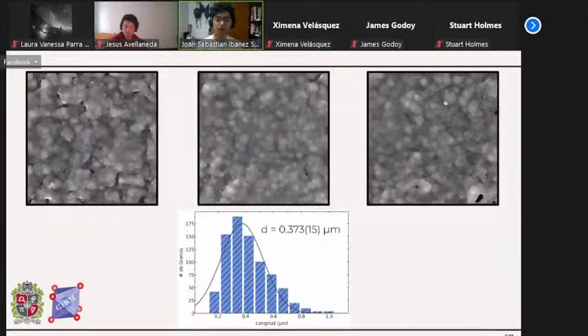Of the distribution, it is also worth noting that the last one, this blue one that I'm showing here, had a larger spread than the other two, and we believe that this is due to the large temperature jump that we made. We went directly from 900 degrees Celsius up to 1100 degrees Celsius, while in the first two sintering processes, the difference was only 50 degrees Celsius.